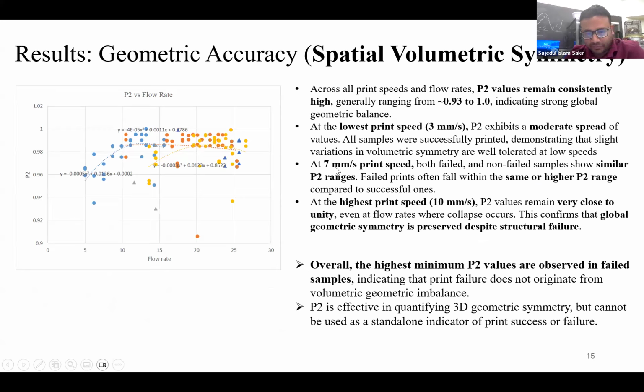But when we are changing the speed to 7 millimeters per second, sometimes it fails, sometimes non-fail samples show a similar range of P2 values. But when we are changing it to 10 millimeters per second, then P2 values remain very close to 1. This confirms that the global geometry symmetry is preserved despite structural failure. So that means the P2 is also like P1, structural failure is happening, but the geometric symmetry is okay.